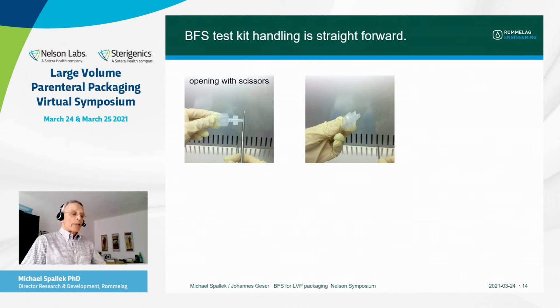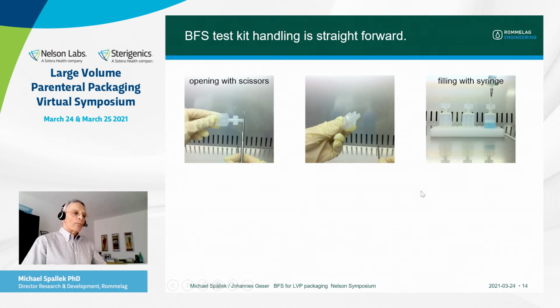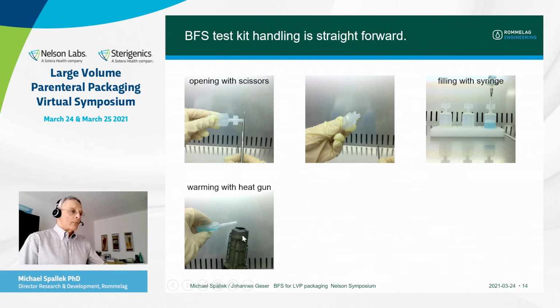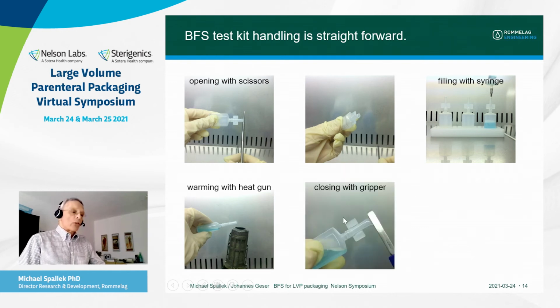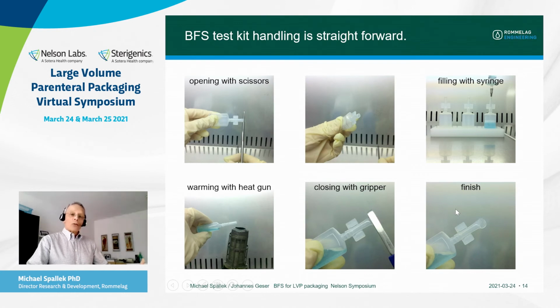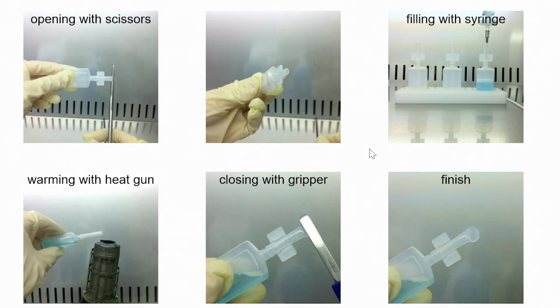Test kit handling is straightforward. You open the container. This is the 10 ml test kit container. You cut it open. You fill it with a syringe or a burette. You warm it up with a heat gun, just the top of it, and you close with a gripper, and you thereby nicely seal the container. Now you can transfer the container to the stability chamber or do the compatibility testing. You can close and reopen the container several times, extract some solution, etc. So that's quite easy, especially if you are very short in active substance in formulation. This gives you a very straightforward testing method and allows good material selection.